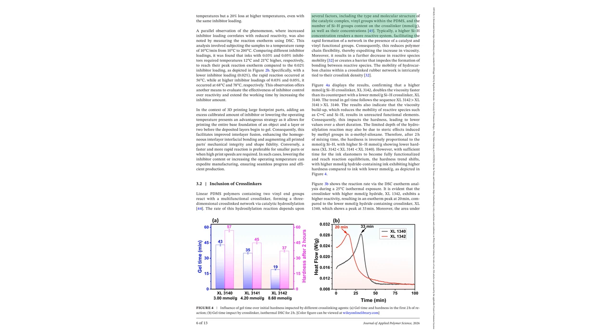The researchers used 3 different crosslinkers, designated XL1340, XL1341, and XL1342. These molecules vary in their content of reactive hydride, SiH, groups, measured in millimoles per gram, increasing from XL1340 to XL1342. They found that a higher concentration of SiH groups makes the system more reactive. The ink with the highest hydride content, XL1342, gelled in just 19 minutes, while the ink with the lowest, XL1340, took 43 minutes. This makes sense. More reactive sites mean the network forms faster.